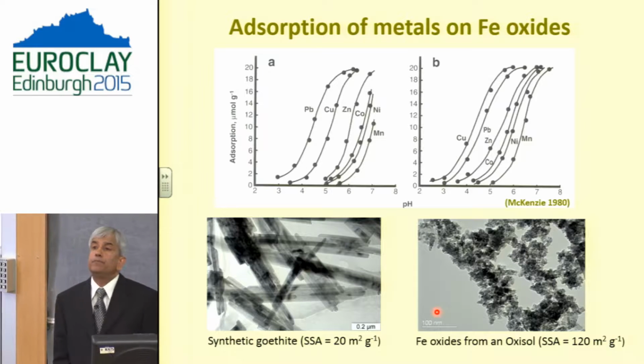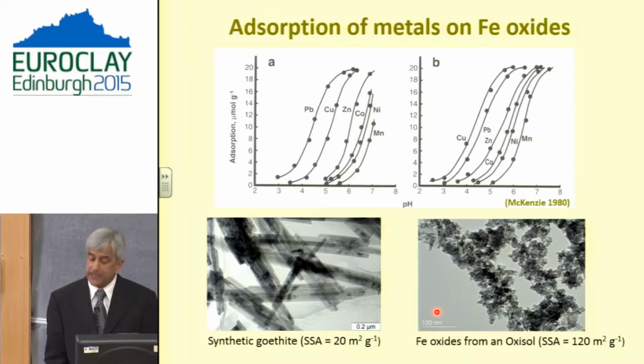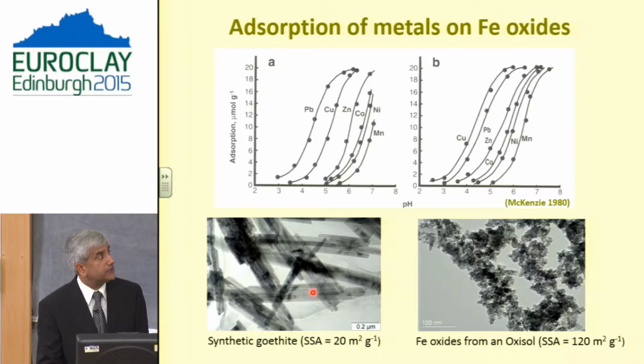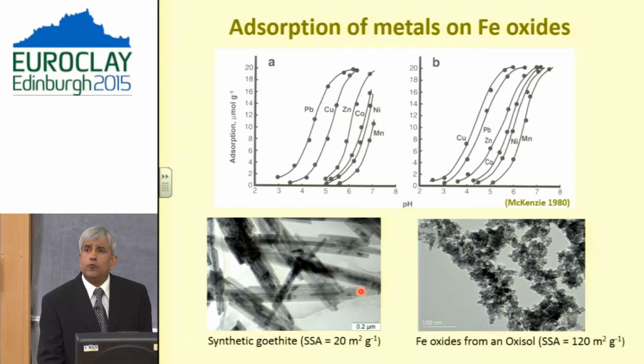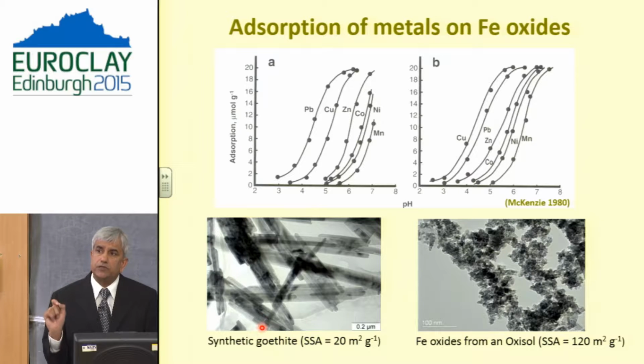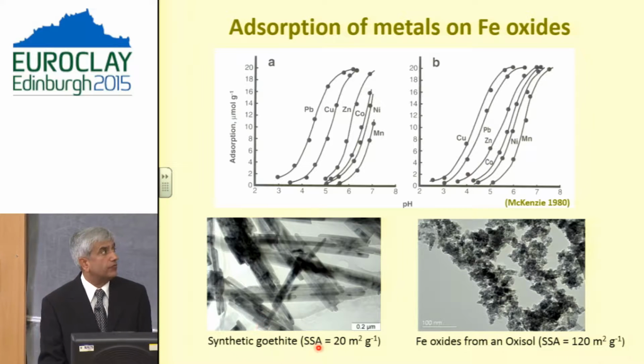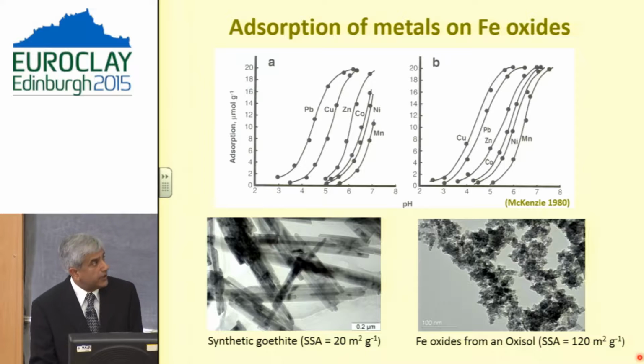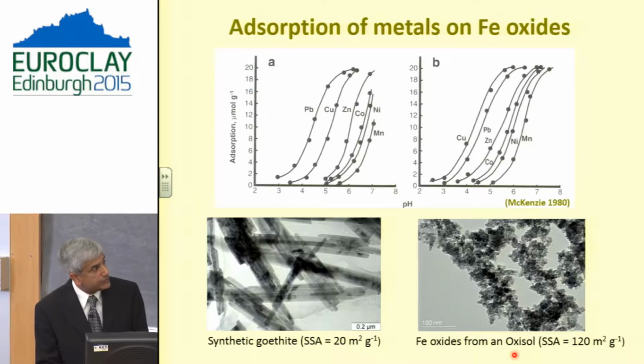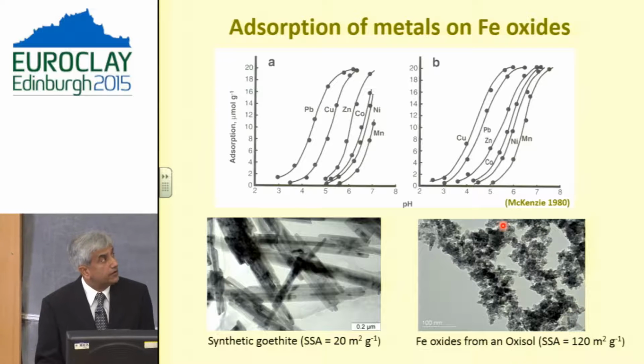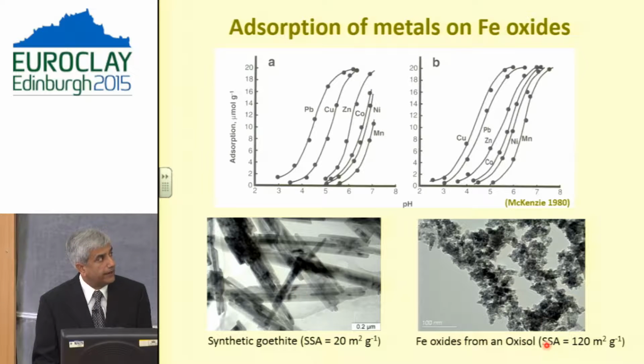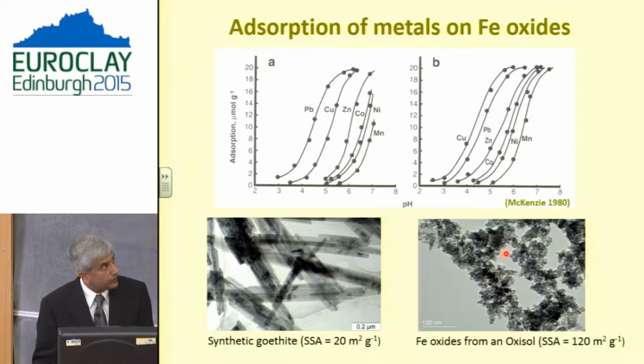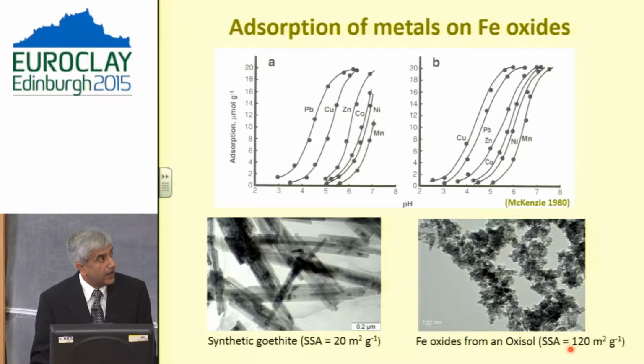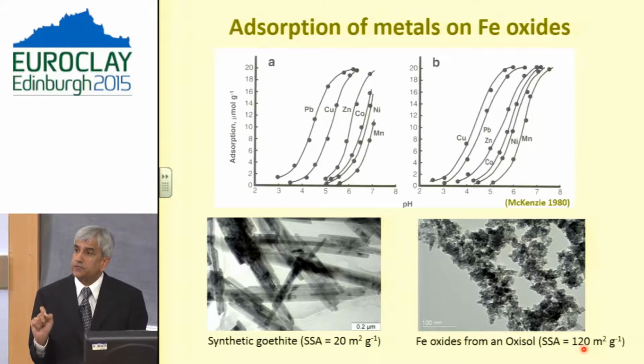When we look at the adsorption of these trace elements on iron oxides, I just want to make the point that often when we synthesize goethite, we make much larger, perfect crystals with very small surface area. Similarly, if you look at the same sort of material from soil, the crystal is nowhere near as well developed as in the pure system, and is much smaller, probably with a lot more defects in the structure, and also has a much larger specific surface area.